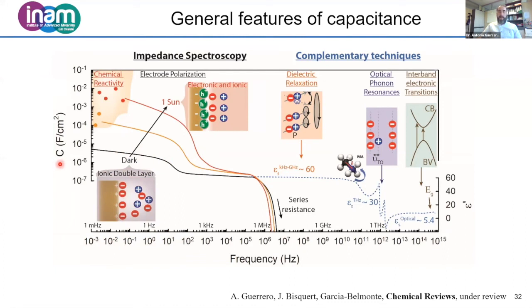So we are probing the electrode polarization of our device. In this ionic double layer, what we have is the typical ions close to the contact. The charge is compensated by the electrodes. And then we have the typical diffuse layers and so on.